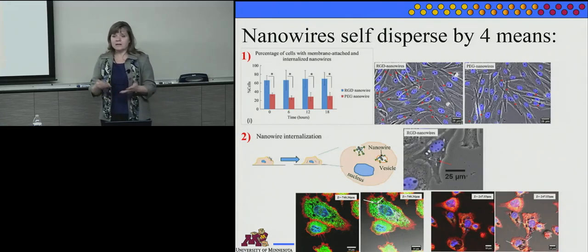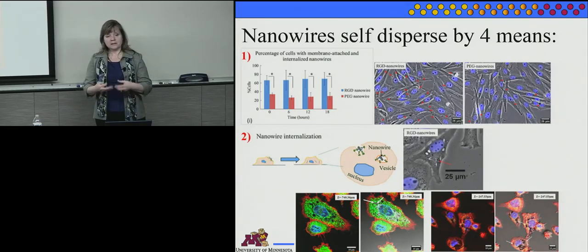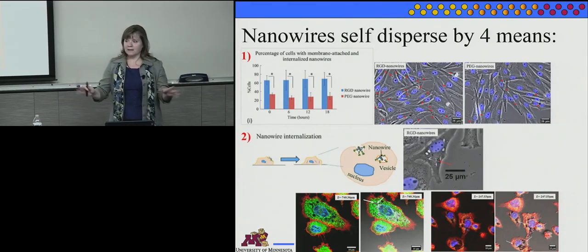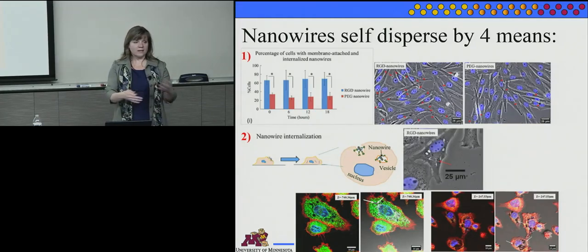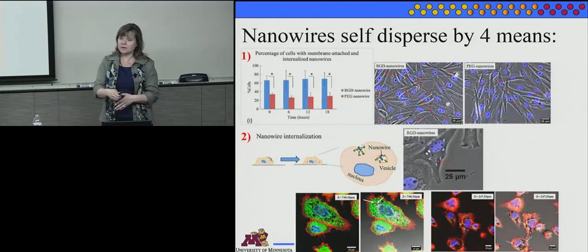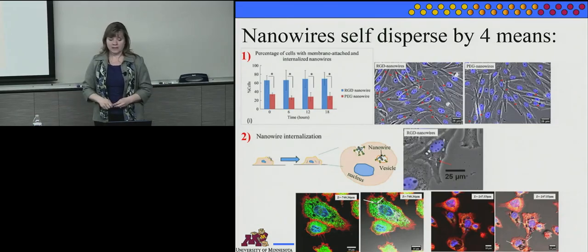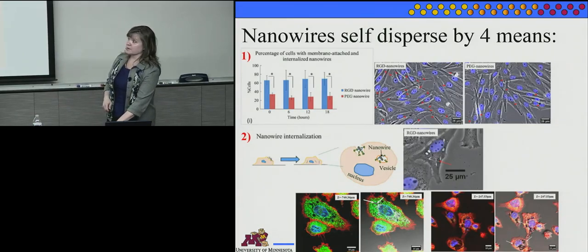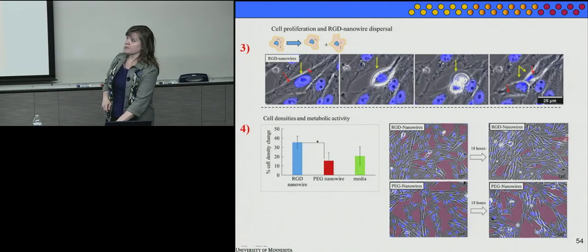So by the end of a normal period of time, let's say 24 hours, most of your population ends up with a nanowire in every cell because they're breaking up the clusters, dividing, and adhering. Every new cell that runs into a nanowire adheres to it. When it divides, it continues splitting, and we end up with a lot of nanowires dispersed throughout our cell population.